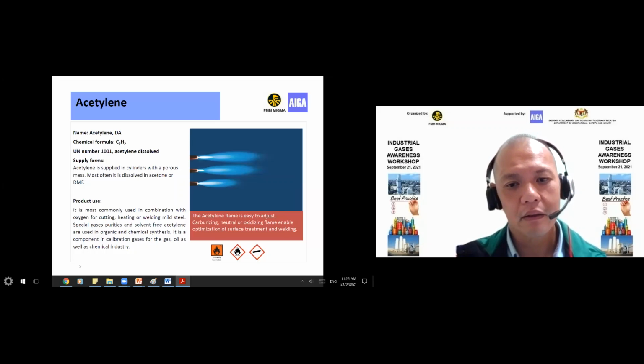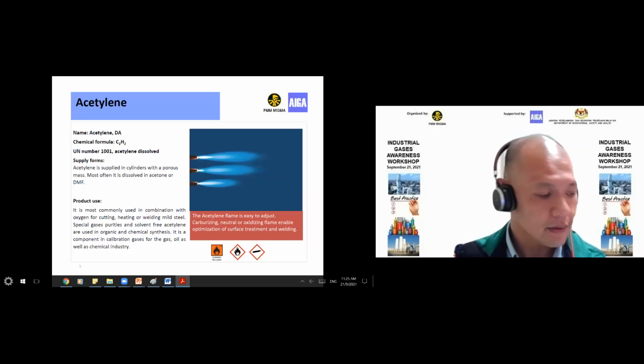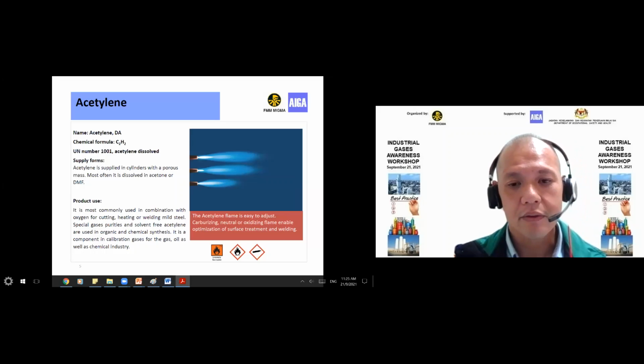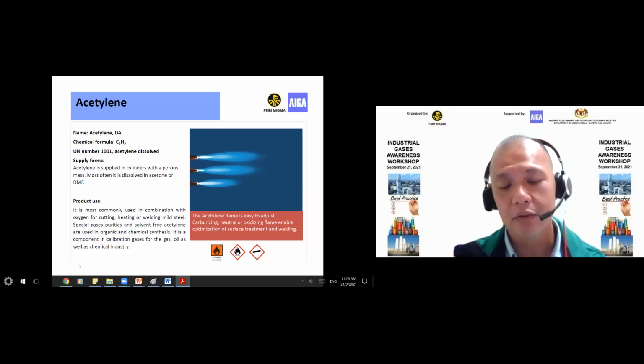Why are acetylene flames more preferred? Basically, the oxyacetylene flame gives you the highest flame temperature. You can imagine that when you see a flame that is deep red or orange in color, the temperature range goes up to 600 to 800 degrees Celsius. That is the normal orange flame that we generally see.